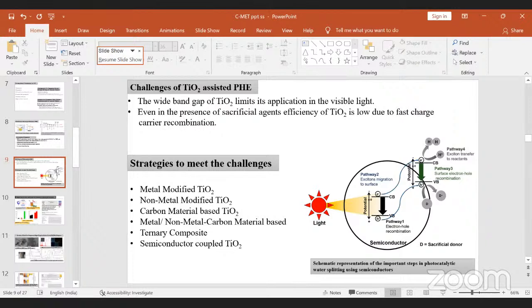We have seen in the last slide what the challenges of TiO2 are for photocatalytic degradation, and in PHE, that is photocatalytic hydrogen evolution, again the same limitations are there: the wide band gap of TiO2 limits its application in visible light, and even in the presence of sacrificial agents, the efficiency of TiO2 is low due to fast charge carrier recombination.